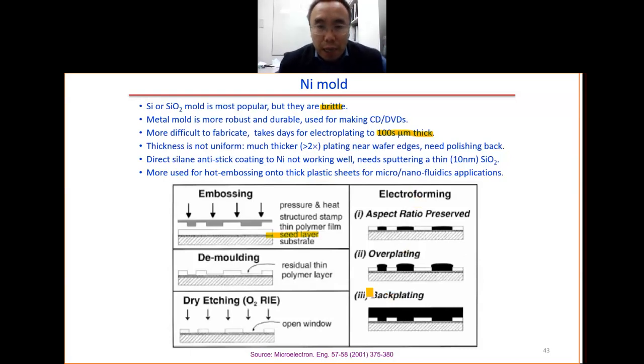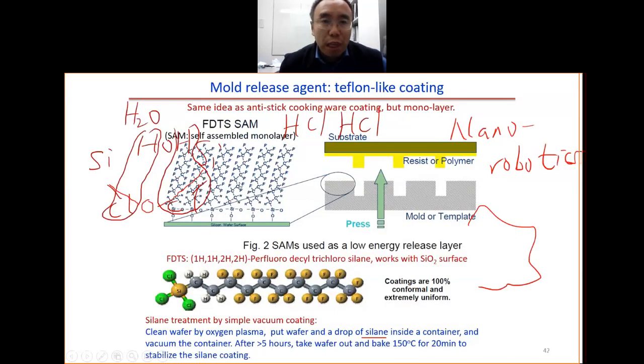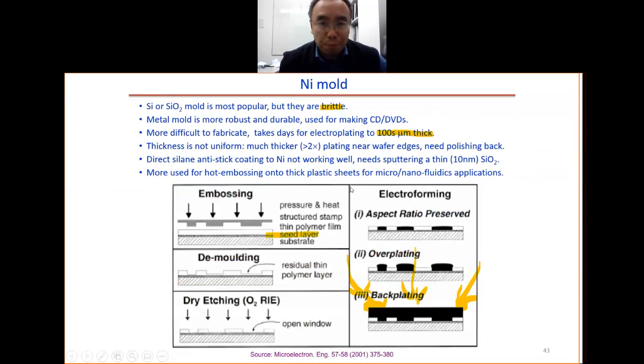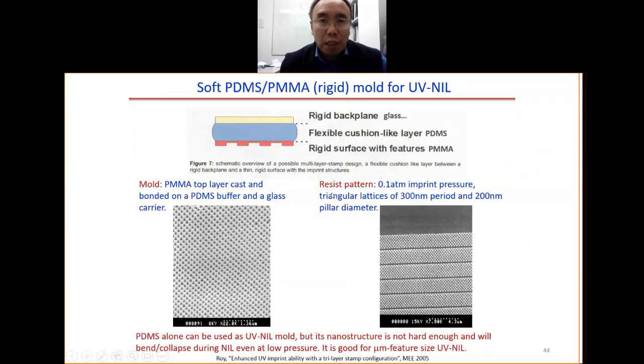Another problem is that the edge plates faster than the central part. You can imagine when you do the plating, you get more ions to the wafer edge than to the wafer center. So the growth at the edge will be faster than the growth at the wafer center. You need a polish-back process. Another problem is that nickel is not very good for the anti-sticking coating. So what you can do is coat a layer of silicon dioxide, then you can do this process to make the surface a low surface energy. And this is the nickel mold.